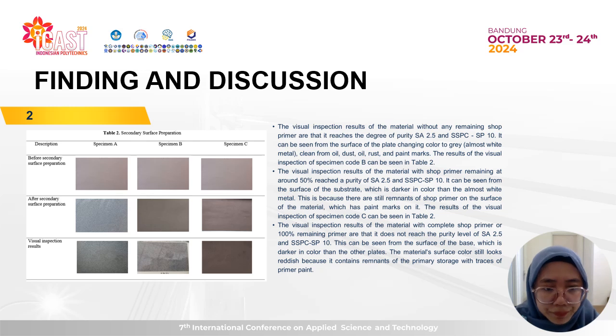And the last specimen, code A, the visual inspection result of the material with complete shop primer, or 100% remaining primer, is that it does not reach the purity level of SA 2.5 and SSPC SP10. This can be seen from the surface of the base, which is darker in color than the other plate. The material surface color still looks reddish because it contains remains of the primary storage with traces of primer paint.